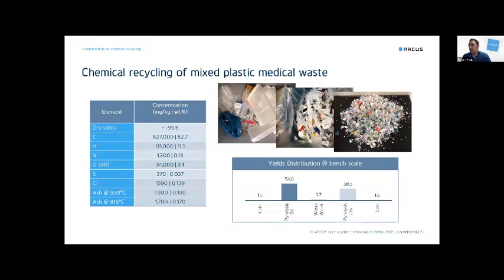And on the right side, you see some pictures of different medical plastic waste in different forms. So you see some packaging and you see some devices at different particle sizes; after some pretreatment, which is sometimes required for a chemical recycling process. And finally, on the bottom, you see a typical distribution of products. And what is important to mention here, more than 50% of your input coming in, including contaminants, is converted into the pyrolysis oil, which is finally the recycled feedstock for further conversion afterwards.